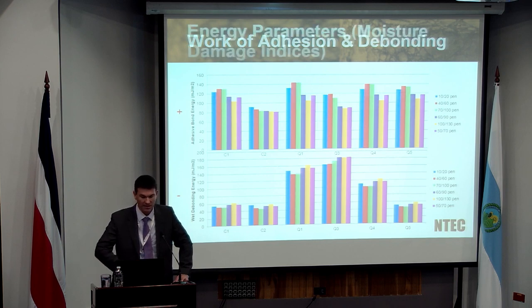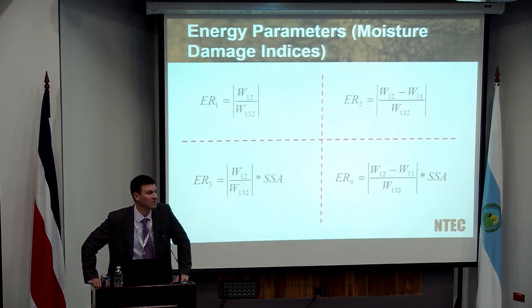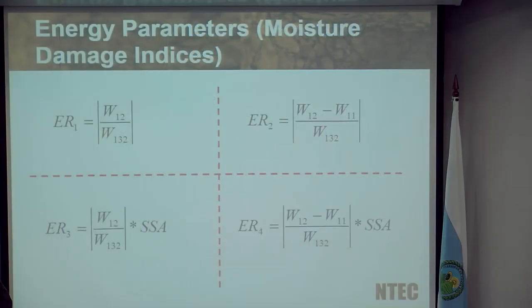We also, as I mentioned, would want to look at those energy ratios, and I talked a little bit originally about the one in the top left-hand corner. We can play around with these energy ratios. Although the one on the top left-hand side is a kind of sensible one, it's got dry adhesive strength or dry adhesive energy divided by the wet debonding energy. We can also play around with the one on the right-hand side, which is saying, well, what happens to the bitumen?